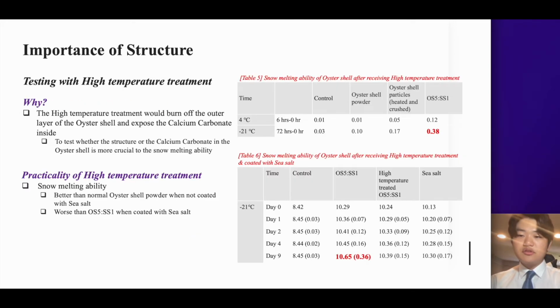The importance of structure was confirmed in the experiment with heat-treated oyster shells. Heat treatment was performed to expose calcium carbonate contained in the oyster shells. I performed experiments to examine if the ice melting performance improves when oyster shells were heated at 1000 degrees Celsius to expose more calcium carbonate. When the heat-treated oyster shells were ground, it could be seen that the heat-treated oyster shells exhibited a higher ice melting rate compared to those without heat treatment.